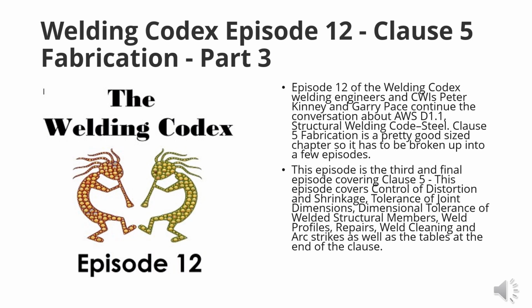Okay, so which brings us to arc strikes, 5.28 arc strikes. Arc strikes outside the area of permanent welds should be avoided on any base metal. Cracks or blemishes caused by arc strikes shall be ground to a smooth contour and checked to ensure soundness. And arc strikes are a big one in any code, not just D1.1. You don't want to be striking an arc outside the weld zone because it can lead to stress concentrations